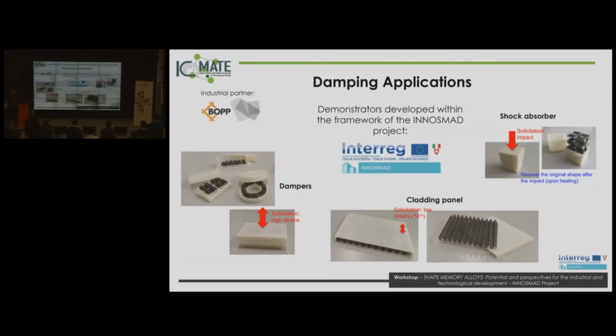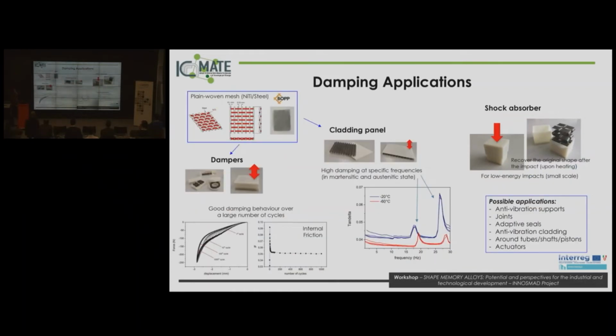In the field of this damping, we have developed some demonstrators also within the framework of the INNOSMAD project, and you can find the demonstrators down here, which are some dampers, a cladding panel for the damping of diffuse vibrations, and a shock absorber for low energy impacts. The dampers and the cladding panel have been developed through the use of plain woven mesh made up of thin wires of nickel titanium and steel, produced by BOPP, which is a Swiss company.